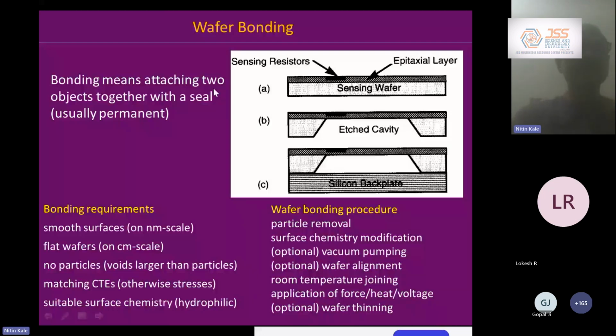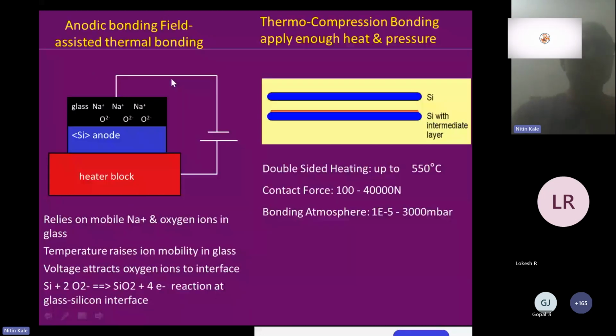So one method is anodic bonding or field assisted thermal bonding. You heat it basically. You apply a voltage across it, and the sodium flows inside, and you have a bonding between the silicon and silicon dioxide, and the two wafers are then going to bond with each other, the glass and the silicon. For thermocompression, you need high temperature, and also you need pressure. So it is just based on these two that the two surfaces are stuck. It has been known that anodic bonding is much stronger because there is a chemical bonding involved, rather than thermocompression, in which there is just a glue which plays the role.